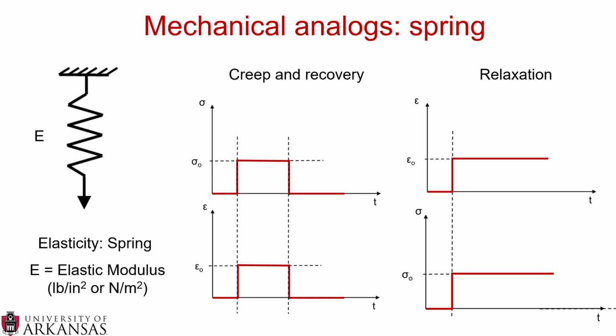So you can see here a fundamental difference between creep and recovery. With the creep, you apply a stress, you measure the strain. When the stress is released, the strain goes to zero. But in relaxation, when you apply a strain, that constant strain results in a constant stress being recorded. So this is a spring mechanical analog.